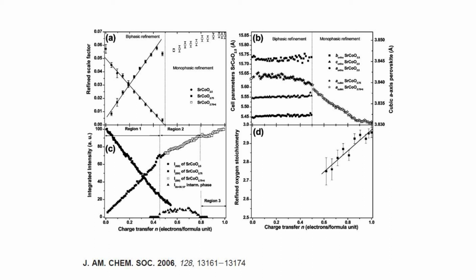But when we reach this point, something happens. So we stop having two phases, we have just one phase. And in this case, by adding oxygen, we see a change in the lattice parameter. These are the intensity of selected peaks that are the more intense of the different phases. This is the superstructure peaks that appears in this region, and this is the refinement of the oxygen fraction in the last part of the diffractogram. So oxygen 2- is entering the system.